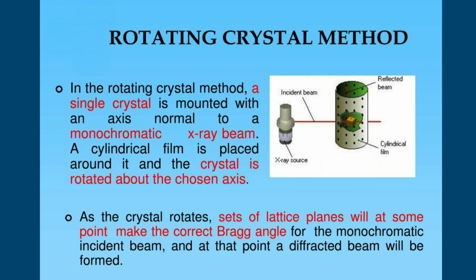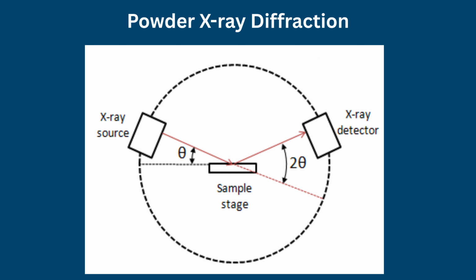The rotation method, also known as the oscillation or precession method, involves rotating the crystal in a monochromatic X-ray beam of known wavelength. Diffraction data are collected over multiple angular positions, producing highly detailed structural information. In powder diffraction experiments, randomly oriented particles generate concentric diffraction rings, whereas single crystal rotation experiments yield discrete diffraction spots that can be reconstructed to determine atomic coordinates.